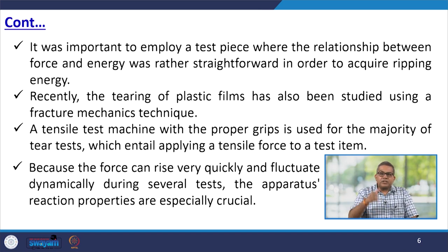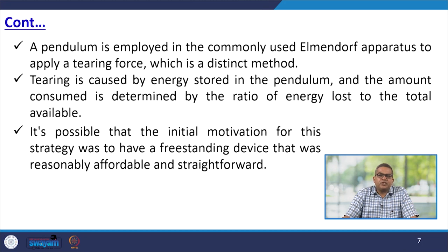Recently, the tearing of plastic film has also been studied using a fracture mechanics technique. A tensile test machine with the proper grip is used for the majority of tear tests, which entail applying tensile force to a test item. Now, because the force can rise very quickly and fluctuate dynamically during several tests, the apparatus response properties are especially crucial. A pendulum is employed in the commonly used Elmendorf apparatus to apply a tearing force, which is a distinct method. Now, tearing is caused by energy stored in the pendulum, and the amount consumed is determined by the ratio of energy lost to the total available. It is possible that the initial motivation for this strategy was to have a freestanding device that was reasonably affordable and straightforward.